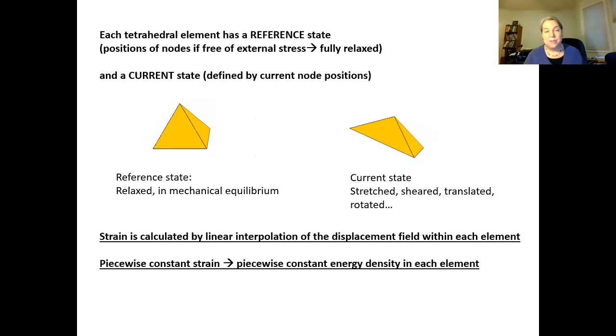I mean, strain has to be calculated for deformation with respect to a reference state. So our model is written such that we have for each element the reference state, that is to say the state at which the material is fully relaxed elastically and has no internal strains. That would typically be when the material is polymerized. That's its shape. And then when it's been heated or stretched or sheared or translated or rotated, those 4 corners of this tetrahedron have all moved to new locations. And then the strain is calculated by linearly interpolating the displacement field from one state to the other.